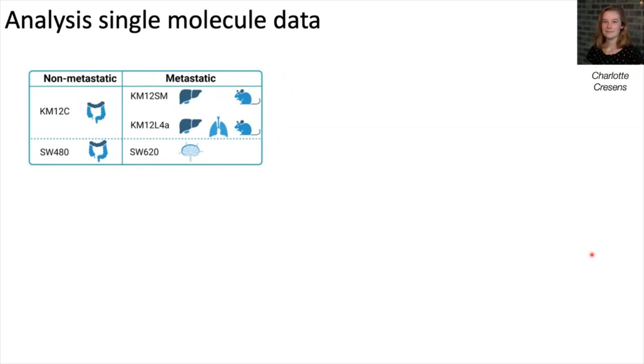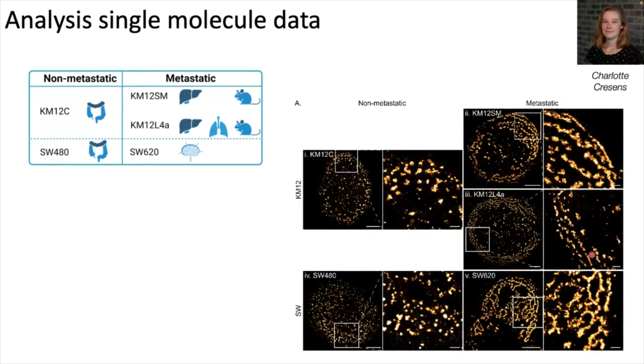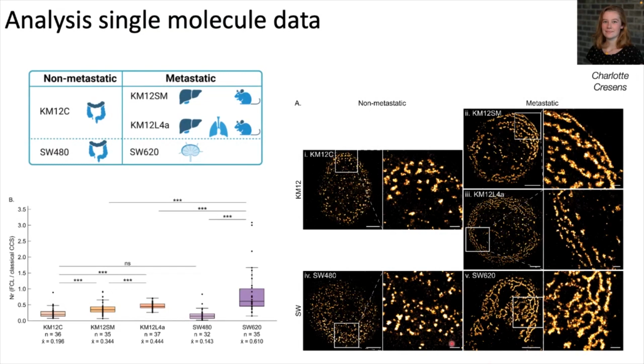And then we just say, okay, is there a relation between the metastatic potential of the cell and these clathrin structures? And in fact, there is. So if the cells are non-metastatic, either the KM12 model or the SW model, you can see mainly the pits, the spherical structures. But then if they have a higher metastatic potential, you can start seeing these flat clathrin lattices. And if we then analyze everything, we just calculate the ratio between the clathrin pits, the spherical structures, and the lattices, which are these more elongated arrays. And we see that for the non-metastatic, this ratio is very low. And when the metastatic potential increases, the ratio increases also. So that means that there are more and more of these flat clathrin lattices in comparison with the non-metastatic.